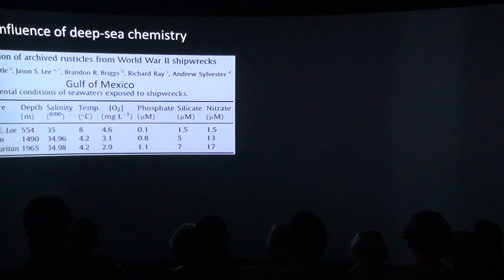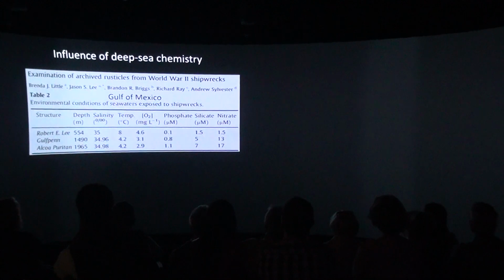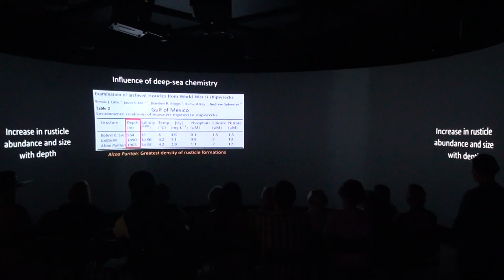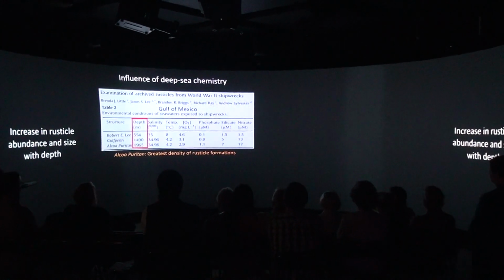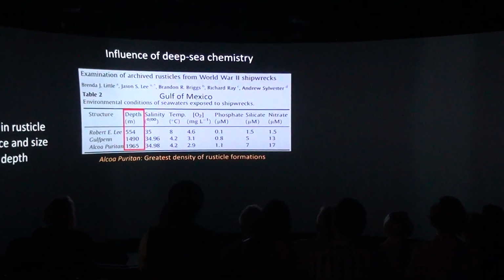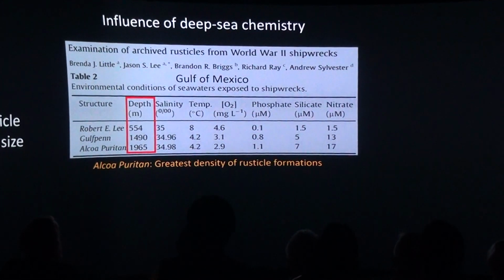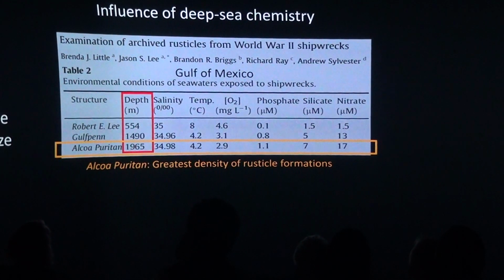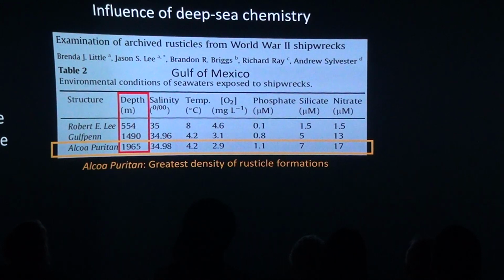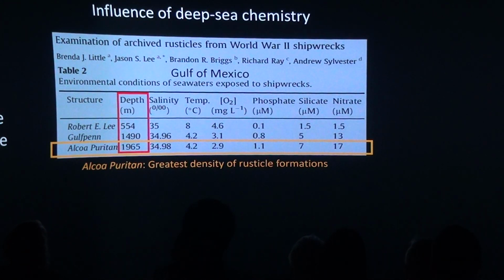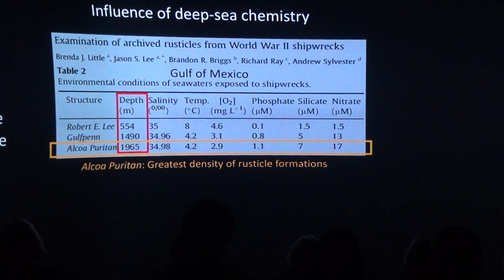So, the influence of deep sea chemistry and how the rusticles increase in abundance with depth. For example, here in this study in the Gulf of Mexico, several shipwrecks, and the deeper they go, the greater the density of rusticle formation, with the Alcoa Puritan having the greatest density. And you can also see that the concentrations of phosphates, silicates, and nitrates in this deep sea, at the Alcoa Puritan, increase, mostly more than 10, 20 times. So there's an influence of deep sea chemistry that is favoring the formation of these rusticles.